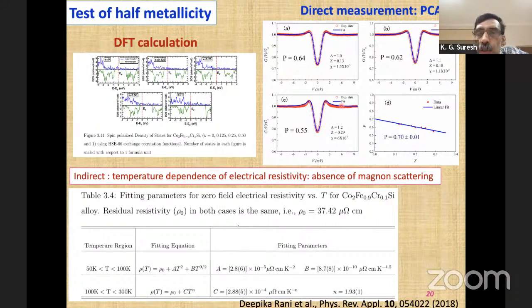So strictly speaking, one has to really do a direct method. That is what I mentioned. This is a PCAR spectrum. The IV characteristic, as I mentioned, what we do is that we take the differential conductance, and from this you can do a fitting. Of course, the fitting is a little complicated, and you can derive the polarization value. In this case, it's something like 70%. I told you that ideally you should get 100%. It's very, very difficult. The only problem with this PCAR is that you are actually using a superconducting metal. You are forming a junction between the half metallic, the suspected half metallic material, and the superconductor. So the experiments are limited because of the transition temperature of the superconductor, and usually if you are using something like niobium, you will be able to get the data only below something like 3 Kelvin, 4 Kelvin. So that will be the reliable data.